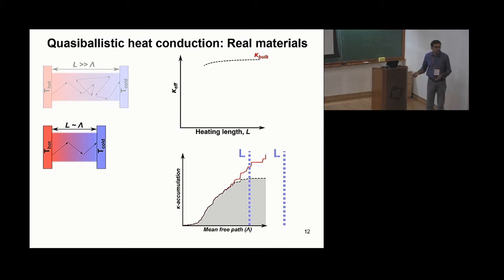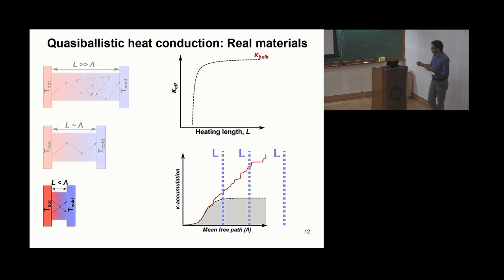So this is what happens in a real material. Because the total contribution, which is the integral over this curve, is smaller than the integral over the red curve, the observed experimental values will start dropping down as you make the hot and cold ends closer together. You can go further into a more strongly quasi-ballistic regime, and you will see further reduction in the observed thermal conductivity.